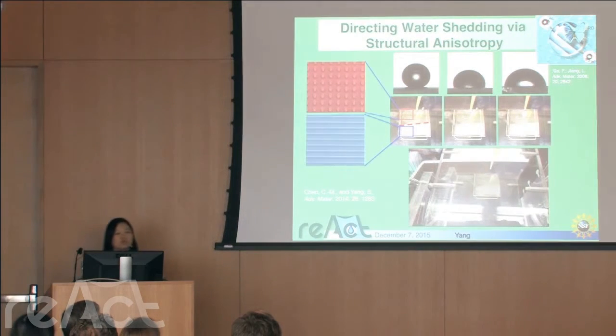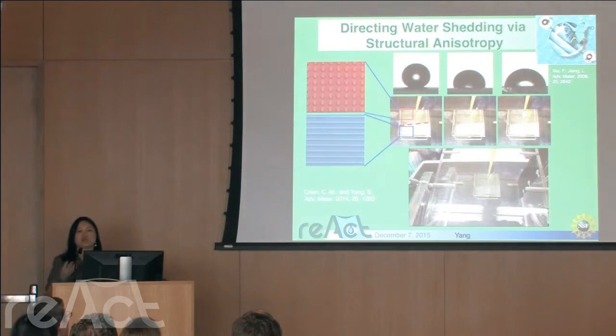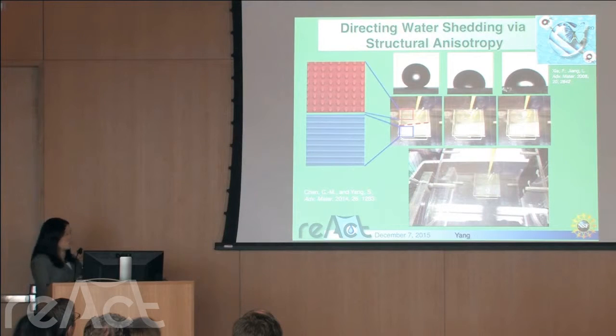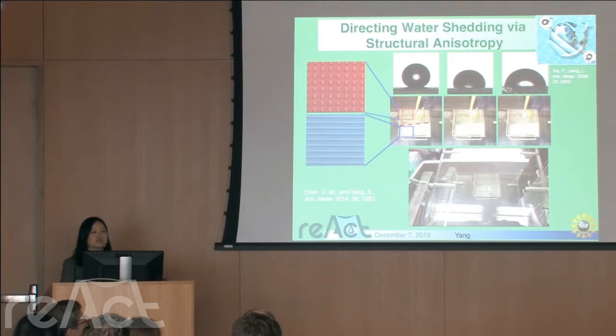And the other example is, if you have the water nucleated, where do they go? Do they just randomly pop out? So our question is, can we actually guide them to go to the place we want to collect? So for example, we have this pillar, which is superhydrophobic, and in this region, you can see here, water does not like to sit on those surfaces. If we shear the pillar, the pillar will be laid down, then you see all these become anisotropic 1D structures, and all the liquid will actually collect on this region. Right? So there are a lot of things we can play around with the geometry and control the guiding of water shedding. And likewise, there are some examples in butterfly wings, which use this mechanism to shed off the water.